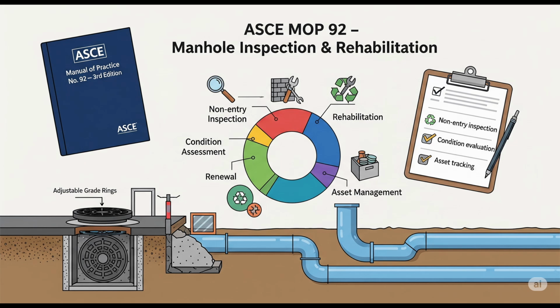Exactly. And then for severe issues, sections of the wall are actually missing, maybe rebar is exposed and corroding, significant structural cracking, deformation. The matrix is going to point towards full depth rehabilitation. That means a structural solution, a fixed cementitious liner, maybe a FIP concrete, a structural polymer liner, or a CIPM liner. Or in the worst cases, it might even indicate that removal and replacement is the most cost-effective option. Wow. So it really guides you from a quick patch to a complete rebuild based on the diagnosis? Precisely. It takes the guesswork out.